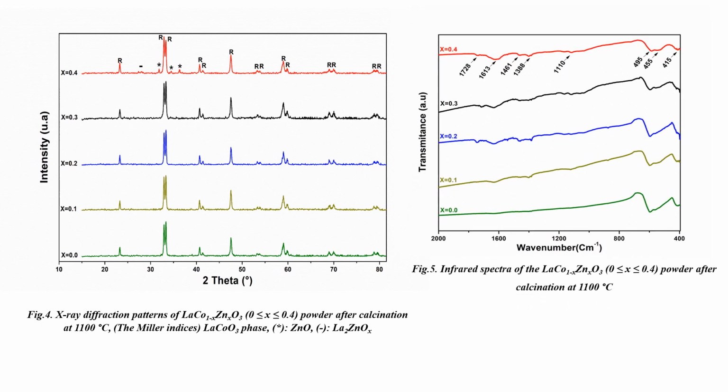The next figure reports the infrared spectra of the samples with different x values. All spectra are rather similar. The infrared bands found at 415, 455, and 595 cm-1 can be assigned to the metal-oxygen stretching vibration of octahedrally coordinated MO6.